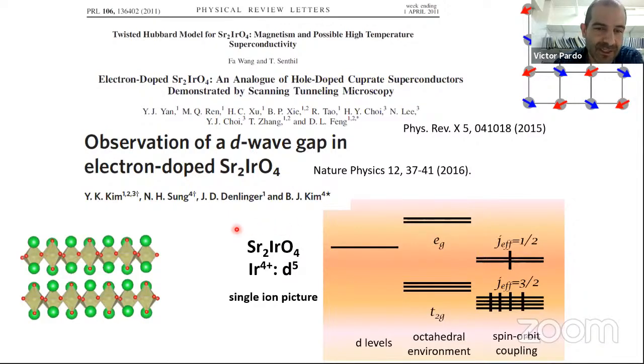The problem to find it experimentally is that these iridates are difficult to dope. So what people have done is surface experiments, and in surface experiments, they can sprinkle some dopants on the surface, and they do measure a d-wave gap with STM or other techniques. They do measure something which could resemble the physics of the cuprates with the same symmetry, but they don't have the smoking gun experiments, say, zero resistance typical of superconductors, because these are very difficult to dope in the bulk. But certainly this points in the direction that, okay, maybe other systems similar to the cuprates can be found.